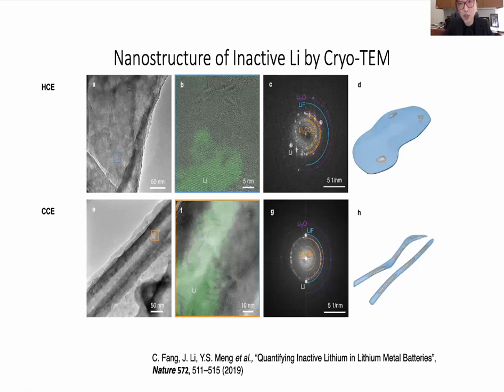On the other hand, cryogenic TEM is also very important because we always have this imagination: okay, SEI is the biggest problem for lithium metal because you grow this interface and the lithium metal is consumed by the SEI. And it turns out, if you don't use the cryogenic imaging, you can't see that these lithium metal are completely encapsulated in the SEI. The SEI contains lithium oxide, lithium fluoride, lithium carbonate. They're very insulating. So when you do room temperature imaging, these compounds will be so unstable that you can't really make the actual observation. The materials are just unstable under the E-beam. Now you have a way to stabilize it.